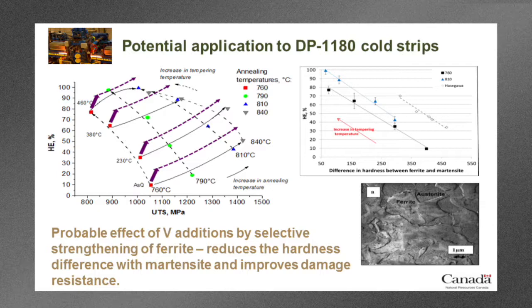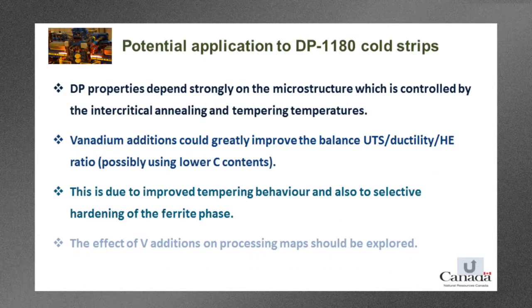So what I'm saying is that the probable effect of vanadium additions by selective strengthening of ferrite will reduce the hardness difference with martensite, and it will improve the damage resistance. So it would be a very, very interesting thing to do to a high-strength dual-phase steel. Let me just make an intermediate conclusion on that.